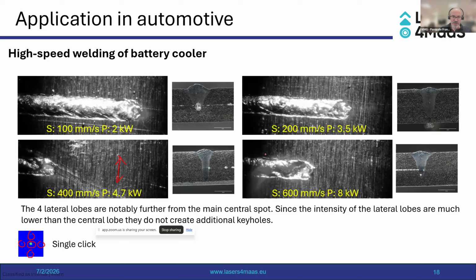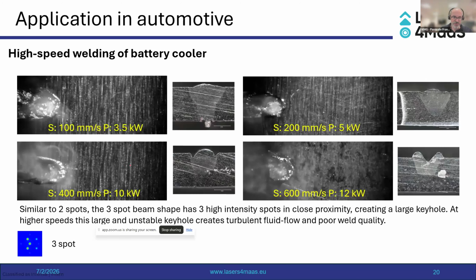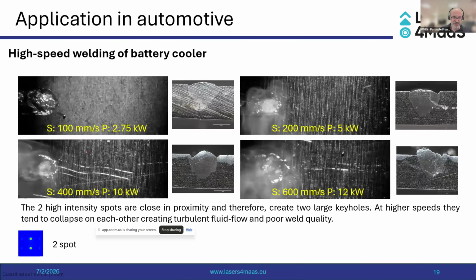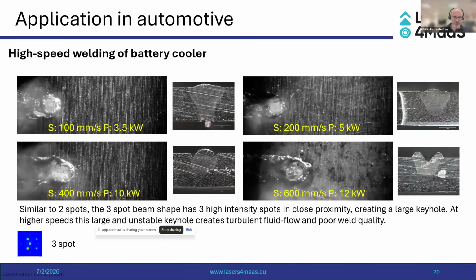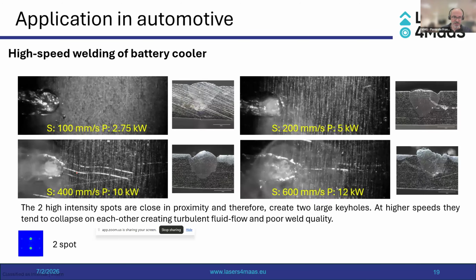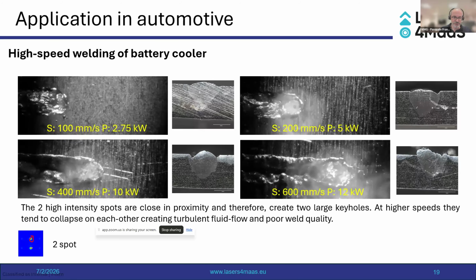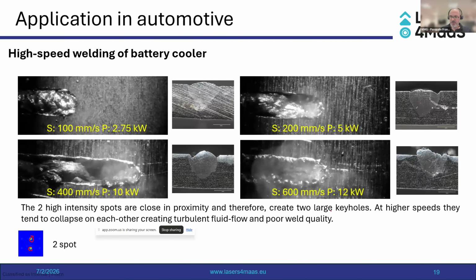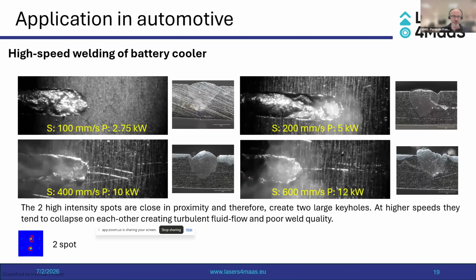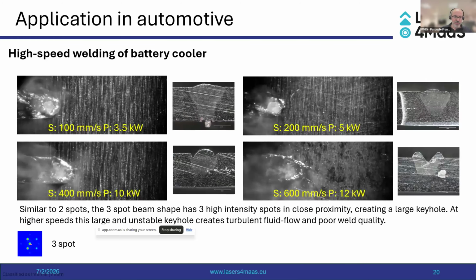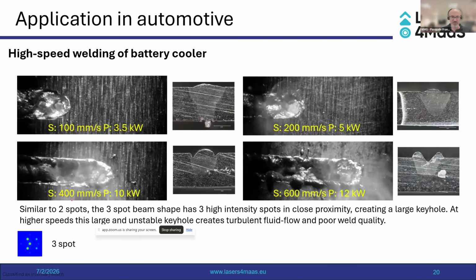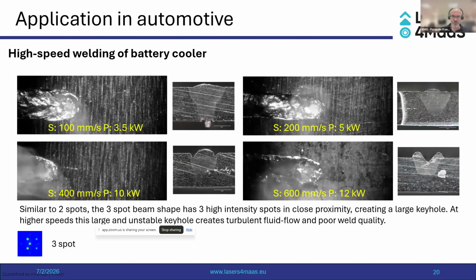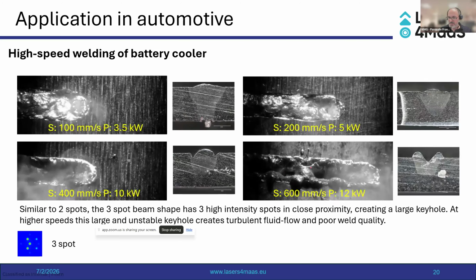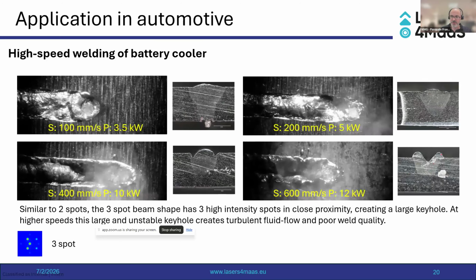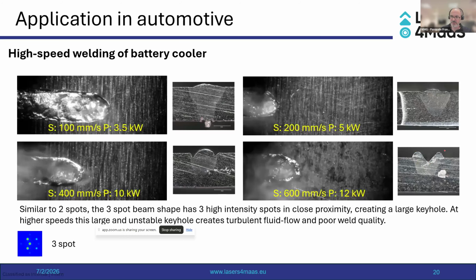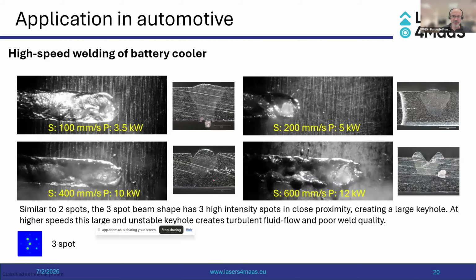So, pretty stable weld. As a comparison, we tested different beam intensity profiles. This is the next one. Here we have 2 dots, top and bottom. Again, the same speed, power has been adjusted, and you can see now how this is becoming unstable. So it's not a very good beam intensity. Another option is to use 3 spots, 1 in front and 2 behind, because theoretically and conceptually, with 3 spots you are enlarging the molten pool in the lateral direction. But in this case, we don't get a stable pool. It's very unstable. There is a massive concavity with 2 massive humps in the weld profile. So, not a very stable process.